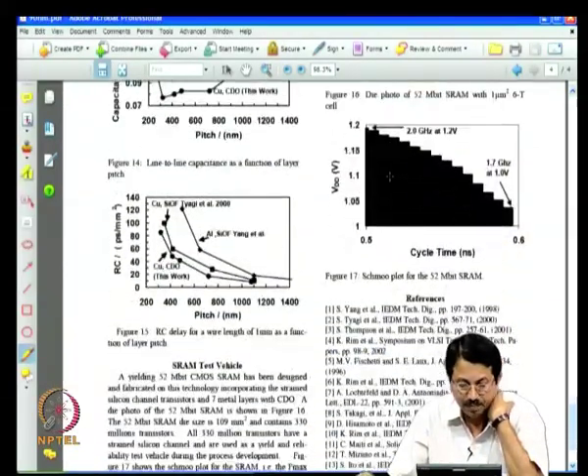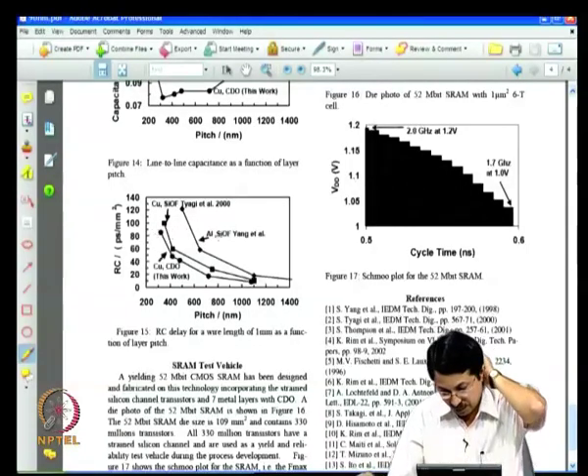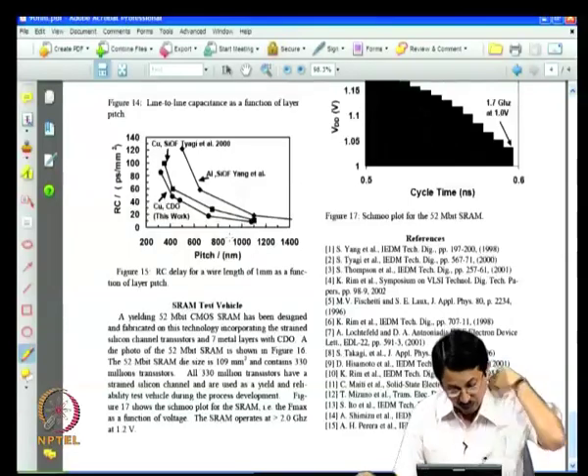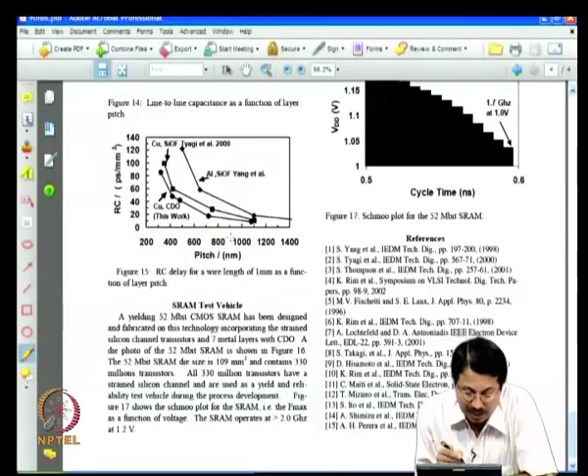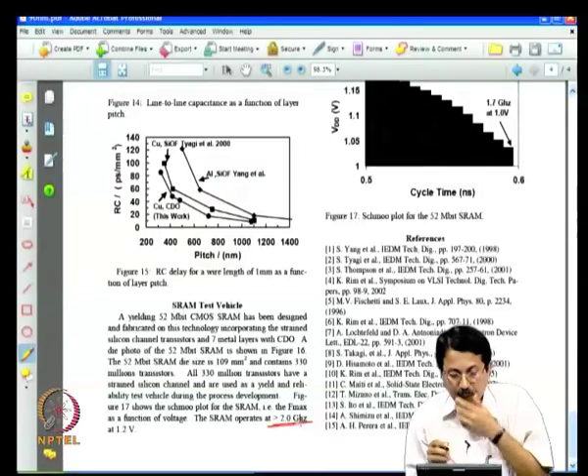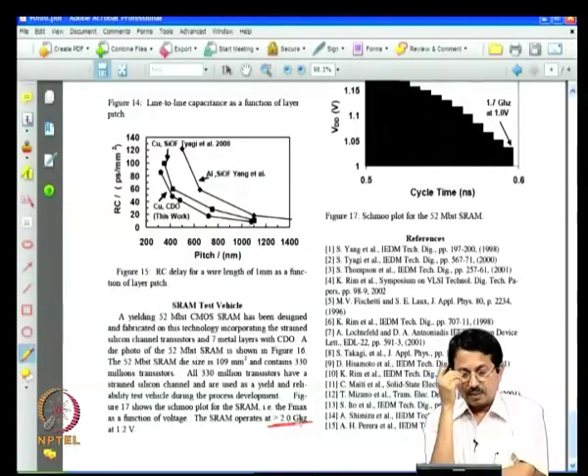And they again show that with carbon doped oxide, you can get significantly lower RC delay as you start decreasing the pitch, as compared to aluminum with fluorine doped oxide, copper with fluorine doped oxide, and this is copper with carbon doped oxide, which is much better. And they have been able to do an SRAM here, and this SRAM operates at 2 gigahertz, which is much higher frequency.